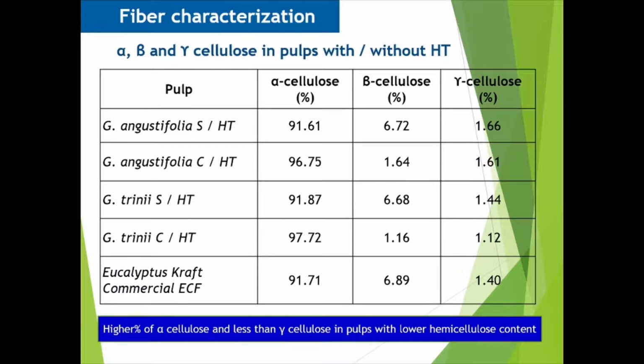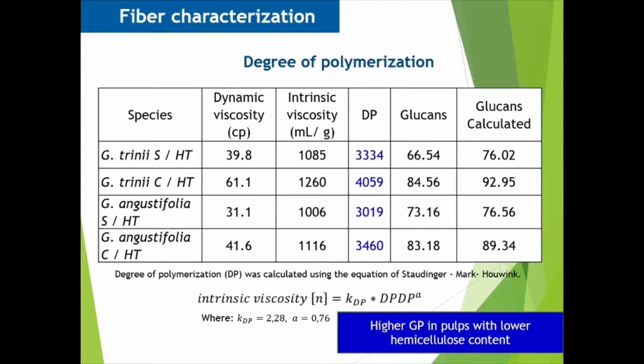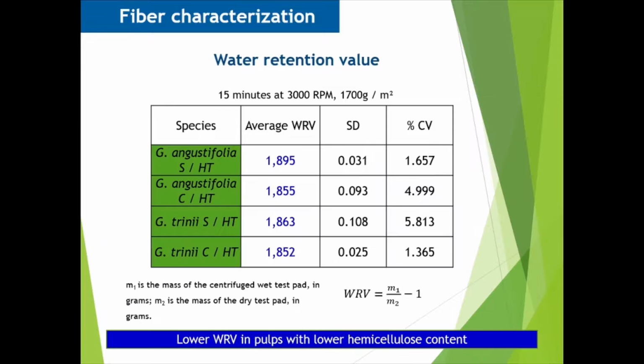Alpha cellulose is related to the higher molecular weight fraction, which was higher in pulps with hydrothermal pretreatment. Beta cellulose is the degraded fraction, which was higher in pulps without hydrothermal treatment. And gamma cellulose is composed mainly of hemicellulose, so it is expected in a lower content in pulps with hydrothermal pretreatment. The degree of polymerization was higher in pulps with hydrothermal pretreatment since they have many monomers in their chains.